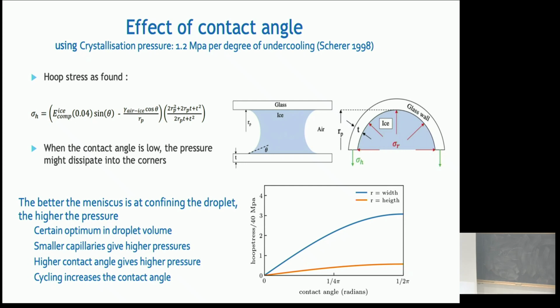So that's the main result of this calculation that you can see here. This is the calculated hoop stress as a function of the contact angle. And so not only do we get the right order of magnitude, we see that it increases with increasing contact angle. And so we've done a study on a very well-controlled system.